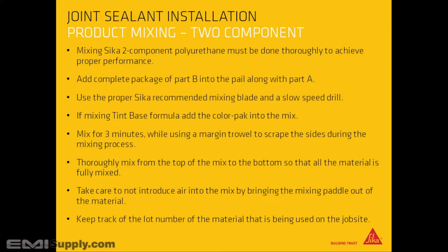2-component coatings. Mixing Sika's 2-component polyurethane must be done thoroughly to achieve proper performance. Add complete package of Part B into the pail along with Part A. Use the proper Sika recommended mixing blade and a slow speed drill. If mixing tint base formula, add the color pack into the mix. Mix for 3 minutes, while using a margin trowel to scrape the sides during the mixing process. Thoroughly mix from the top of the mix to the bottom so that all the material is fully mixed. Take care not to introduce air into the mix by bringing the mixing paddle out of the material. Keep track of the lot number of the material that is being used on the job site.